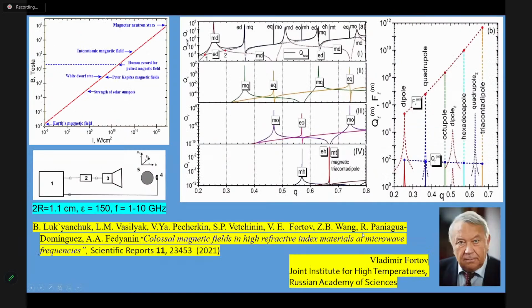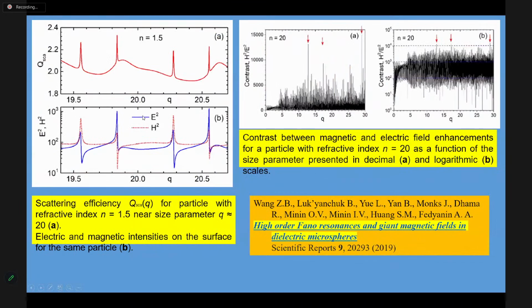Now, if you compare what you can reach with high order Fano resonances, it is easy to obtain 10 to 5 and 10 to 6 and even higher intensities, magnetic intensities and electrical intensities also. So it is possible to create a huge contrast of magnetic field to electric field. It means that, in principle, it is possible to create magnetic nonlinear optics where variation of the refractive index happens due to variation of mu, not epsilon.